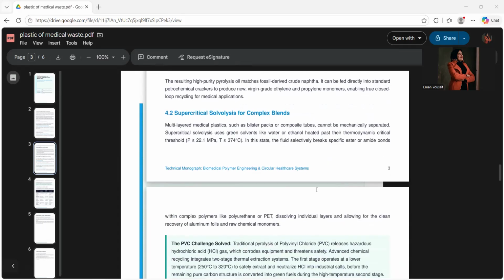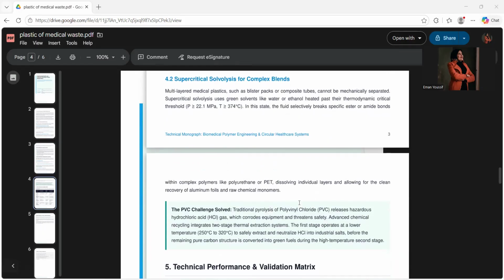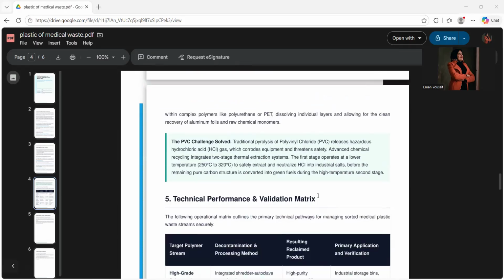Multi-layered medical plastics such as blister packs or composite tubes can't be mechanically separated. Supercritical solvolysis uses green solvents like water or ethanol heated past their thermodynamic critical threshold. In this state, the fluid selectively breaks specific ester or amide bonds within complex polymers like polyurethane, dissolving individual layers and allowing for the clean recovery of aluminum foil and raw chemical monomers.